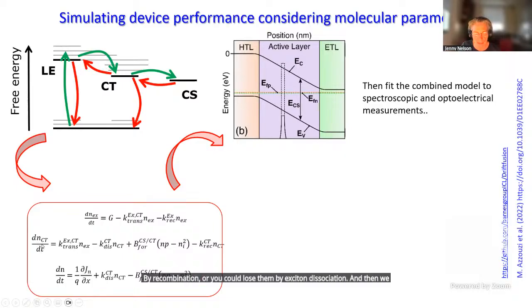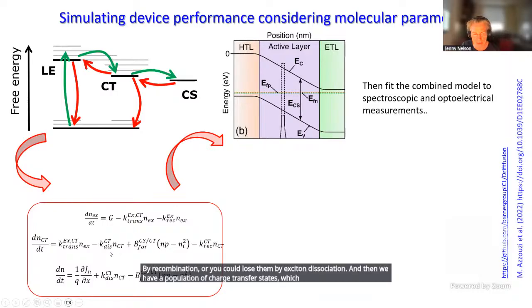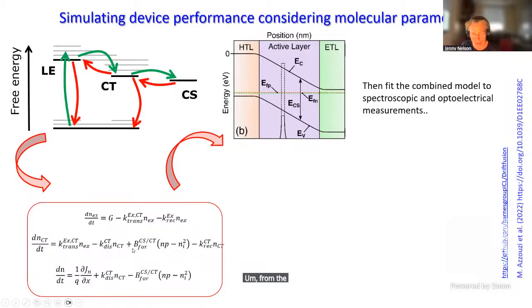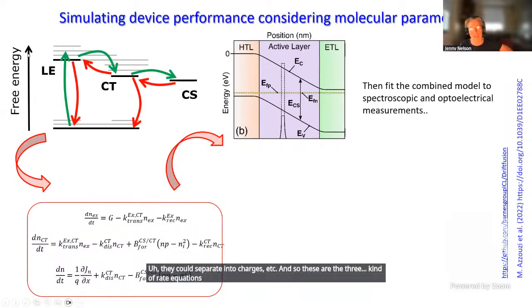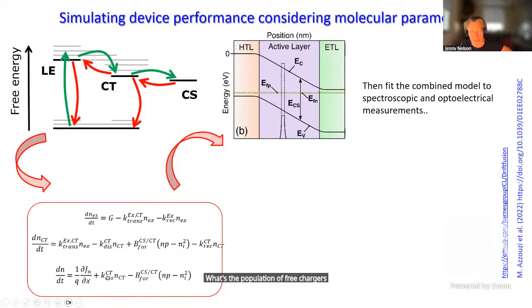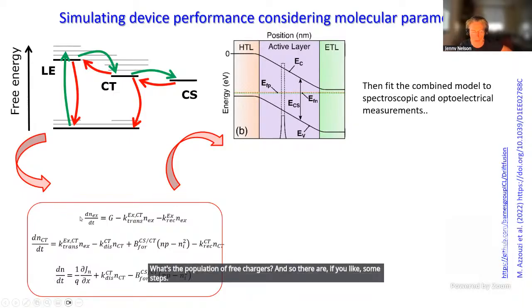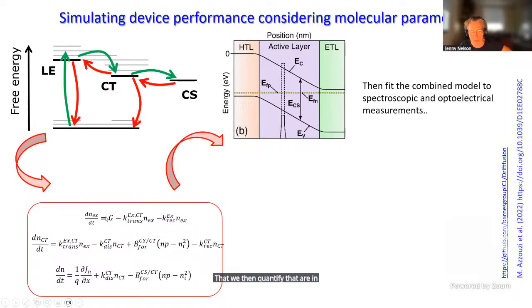And then we have a population of charge transfer states, which are generated from the exciton. They could dissociate, they could separate into charges, etc. And so these are the three kind of rate equations that will take account of what's our population of excitons, what's the population of charge transfer states, what's the population of free charges. And so there are, if you like, some steps that we then quantify that are in between absorbing a photon and generating an electron hole pair. And it's written about in this paper, which is at the link here.